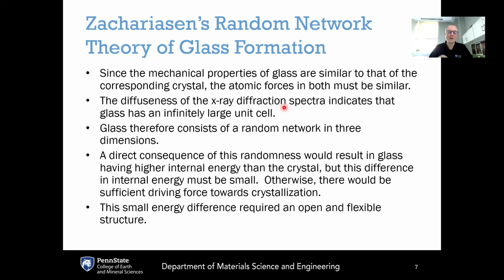So there are no discrete peaks that come when studying glass from X-ray diffraction. And what this means is that there is a lack of any type of long-range ordering in glass. And Zachariasen deduced then that the diffuseness of the X-ray diffraction spectra, meaning this very broad hump that was observed, indicates that glass has an infinitely large unit cell. What this means is that the entire piece of glass is its unit cell, so the structure does not get repeated over space, and that's why we don't see these sharp peaks from the X-ray spectra.